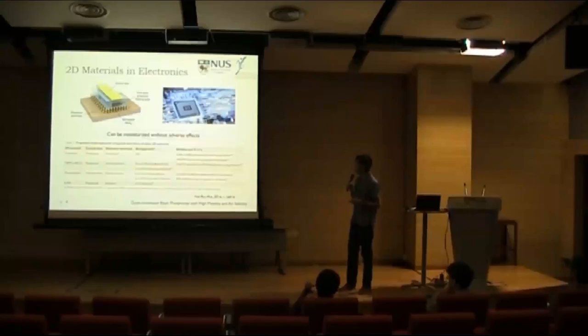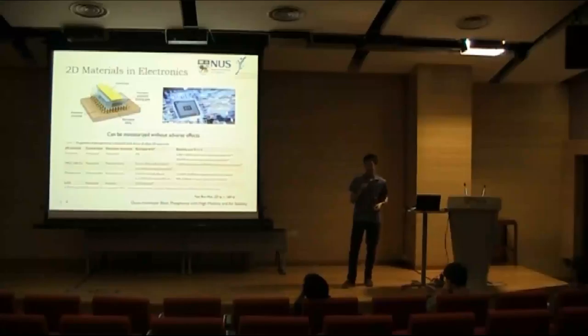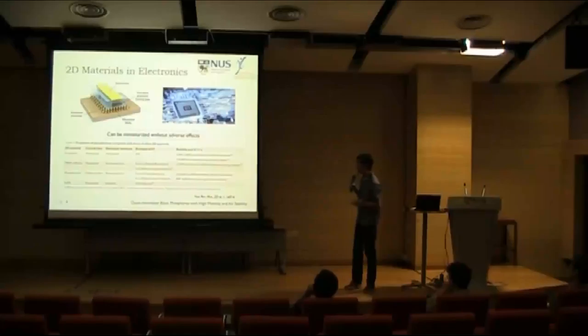And the table below summarizes some of the properties of commonly studied 2D materials. And one of the main indicators used to evaluate the device performance is the device mobility. So the mobility tells us how fast the carriers in a device actually travel. And so the higher the mobility, the better is the device. And at one glance, we can see that graphene has a whopping high 200,000 mobility. And as a reference, our current state-of-the-art silicon transistors have a mobility of 1,400. So it is pretty impressive.